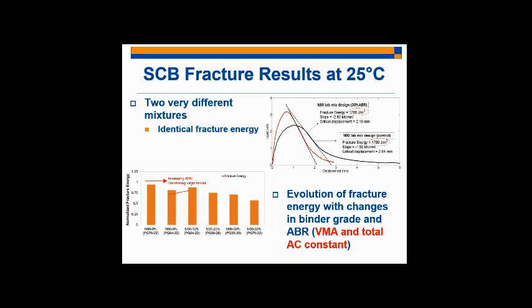And so to the bottom left, you can see basically the progression of laboratory mixes that we've developed. There's about 6 or so laboratory mixes that we've developed in our ICT facility, and you can see that we start off with a control mixture of N90, 0% recycled content, PG grade of 70-22, and then we begin to basically deteriorate the mixture with the addition of RAS. So first we take it to a softer binder grade, right? So the N90 0% 64-22, and we add 10% RAS. Then we add 20% RAS. Then we add 30% RAS, and then we vary the binder.